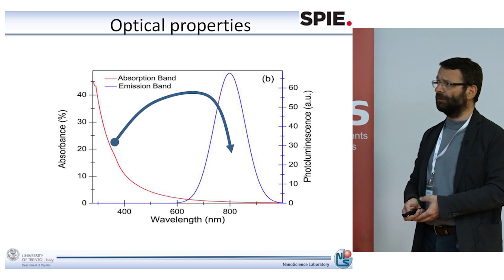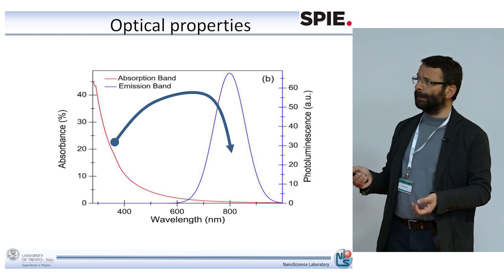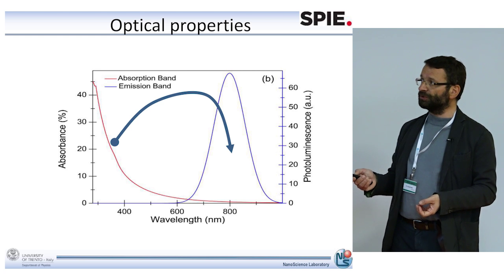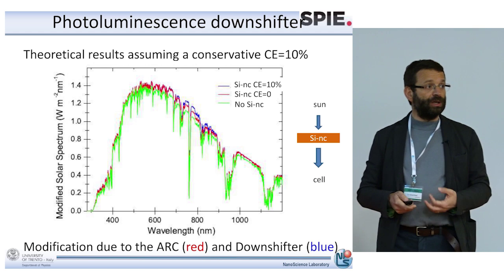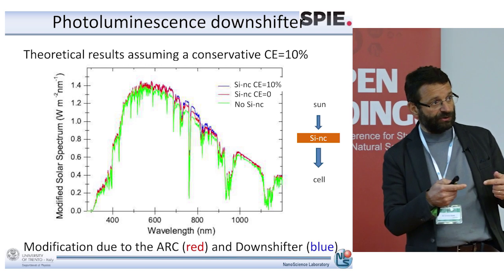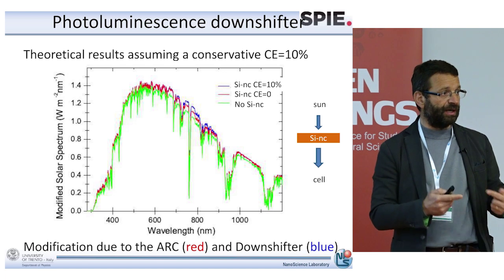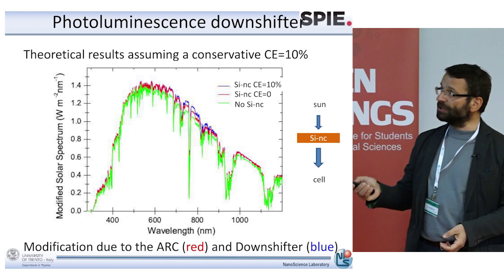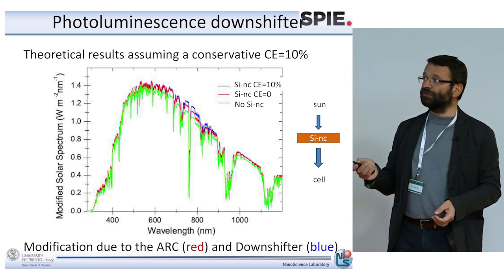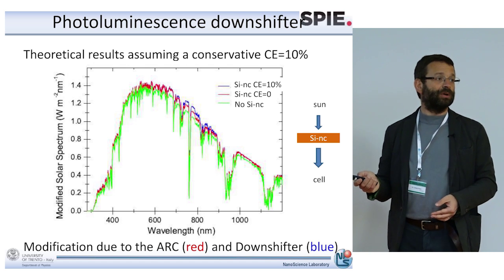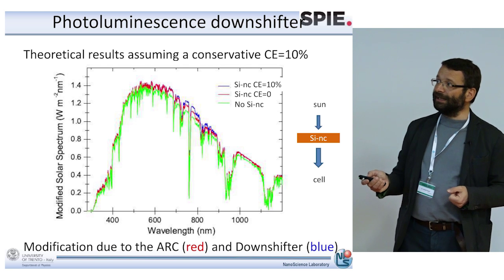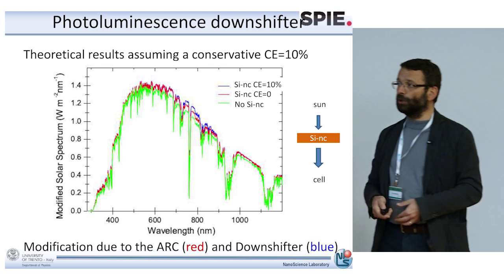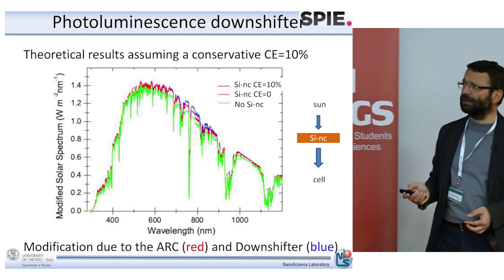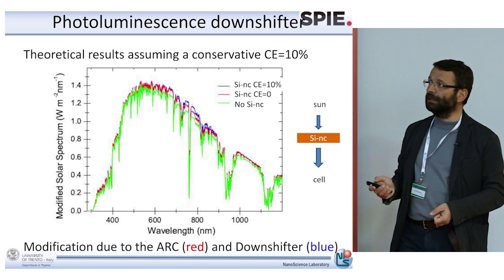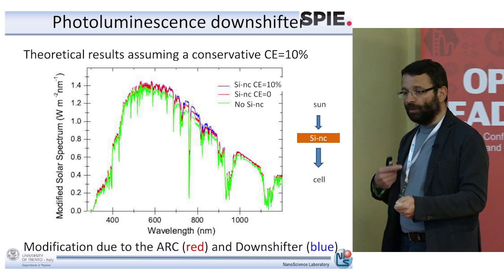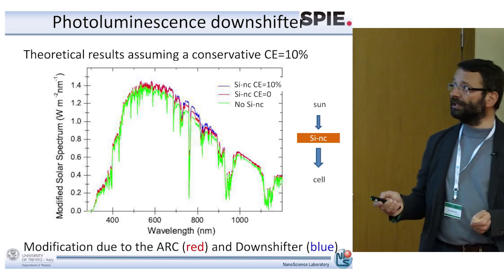Here is the first experiment that we did. So we take a piece of silicon nanocrystals, we put those pieces of nanocrystals on top of a cell, and then we look at how the solar spectrum seen by the cell is modified by the presence of the silicon nanocrystals. So actually what we did was shine sunlight on the silicon nanocrystals, and then we look at how the cell sees this sunlight. And so the green line is the solar spectrum observed by the cell without the silicon nanocrystals. And then we have the red line, that is the spectrum observed by the cell when the nanocrystals do not emit light.